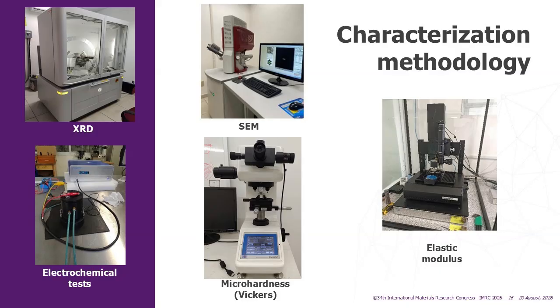The prepared samples were characterized using X-ray diffraction to determine their composition. Scanning electron microscope images were taken to analyze their microstructure, and a Vickers microhardness test was also performed to determine their hardness. Electrochemical testing in SPF was used to determine corrosion resistance, and finally, nanoindentation testing was used to determine the elastic modulus of the samples.